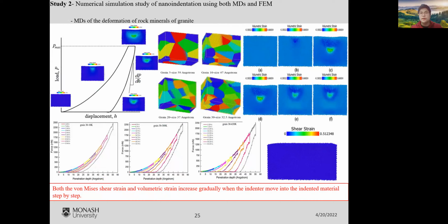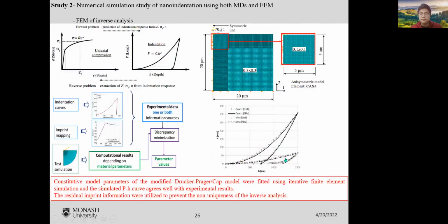Here we show that we use molecular dynamics simulation with two parameters, that is the volumetric strain as well as the shear strain, to uncover the deformation mechanism underneath the indenter.